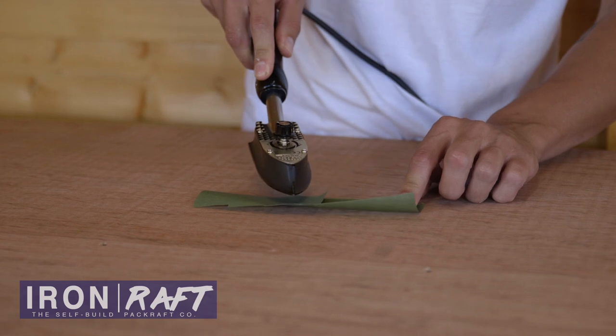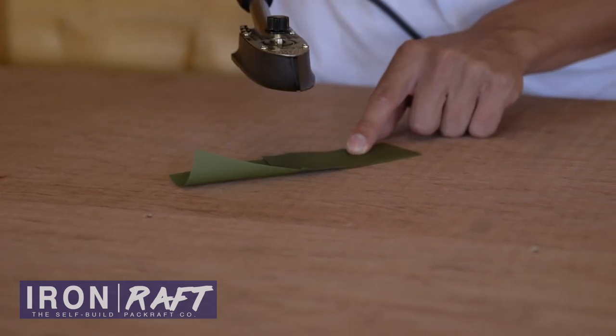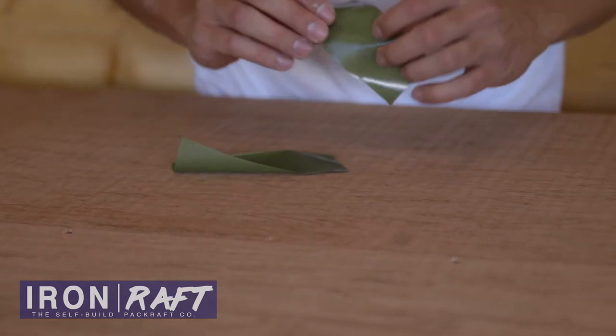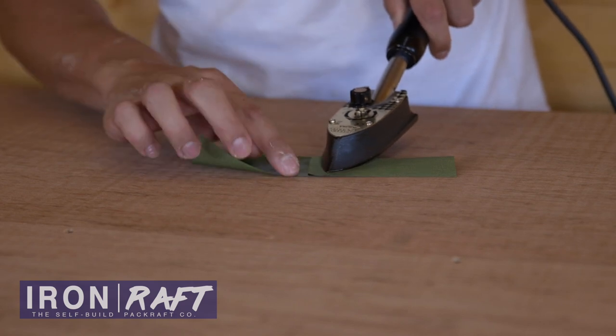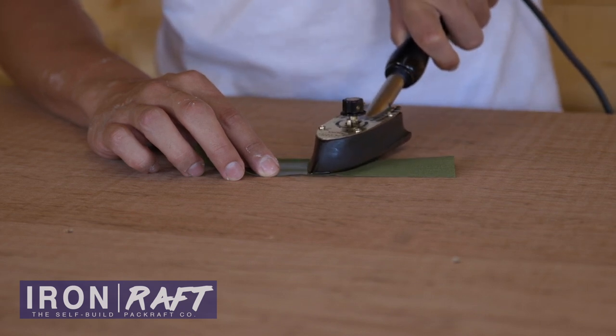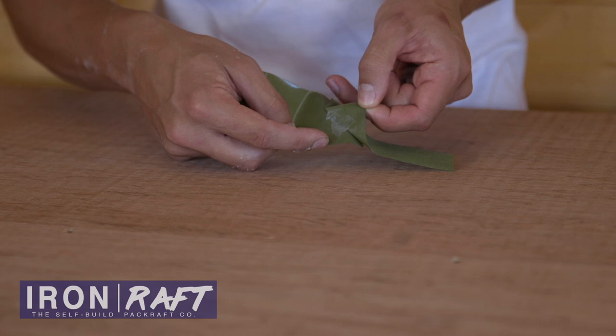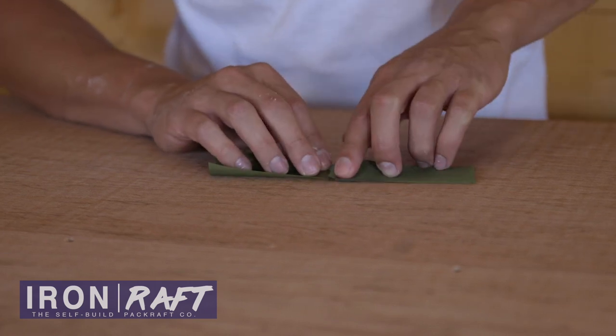I'm just going to show how you can tell if you've got a good seal. You'll see straight away this bit is still sticking up, and as it seals more it starts to stick down and will no longer peel up. I haven't given it enough heat yet and you'll be able to see that I can still peel that apart and nothing is damaged. That's starting to activate but it hasn't completely, so that needs more heat. Again you'll see this little corner here starts to stick down. If you try to pull that apart you've got to be very careful because this retains the heat. It's still pulling apart but you can see it started to activate and it's actually pulling the TPU off the fabric itself. So a little bit more and that would be perfect.